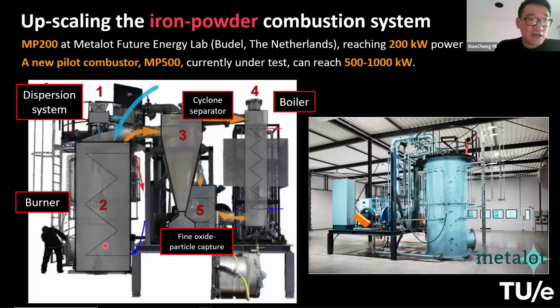While the particles are falling down, they are combusted and release heat. The heat can go through the heat exchanger. And the particles can settle at the bottom of the chamber, and you can see a person can remove this iron oxide powder for recycling. Some of the powder will be taken by the flue gas, so you need a secondary separation, which is the cyclone separator. Due to the centrifugal force inside the cyclone separator, you can further remove iron oxide particles from it. And then the flue gas will go through a secondary heat exchanger to extract the heat from it.